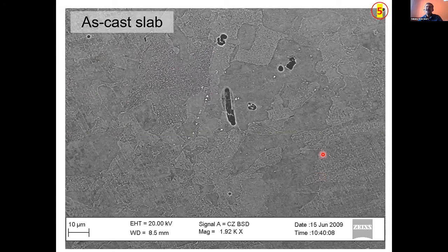What we have noticed when we looked at higher resolution microscopy is that at certain locations there is an enrichment of precipitates and inclusions. If you see quite a wide region here, in this middle part there are small dot-like precipitates. All these white spots are precipitates, and these black features are inclusions like manganese sulfide, titanium nitride with manganese sulfide, and alumina and all those things.